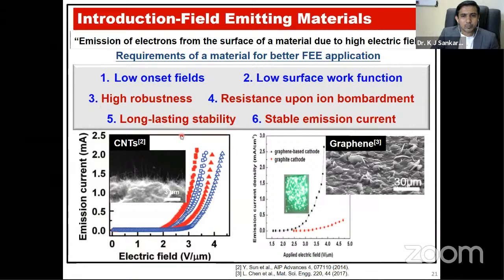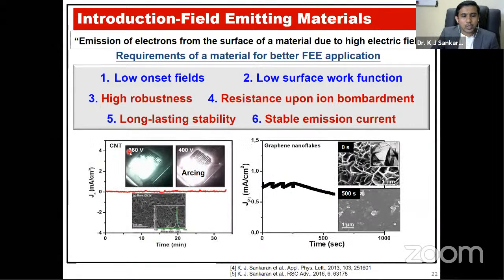But these materials have some drawbacks in other ways. If you apply 360 volts to a CNT, you cannot see a very uniform emission. And once you apply a high voltage, it starts arcing, so the material is completely damaged. Also, regarding long lasting stability with stable emission current, it cannot last for a longer time, only up to 30 minutes. For device applications, this lifetime is really nothing. So we need a long lifetime stability. And coming to the graphene nanoflakes, this is at 0 seconds here, and after 500 seconds, you can see these graphene nanoflakes were completely etched out in the plasma environment.